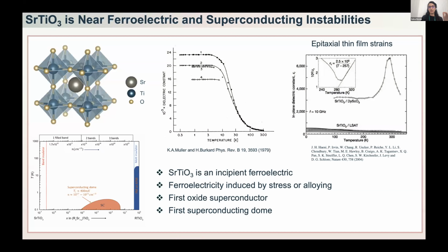Okay, one material system that I am going to focus on in today's talk is strontium titanate. Strontium titanate is close to ferroelectric instability, but it will never become ferroelectric unless you strain it or alloy it with different elements. Also, if we dope it, it will become a superconductor, and it shows a superconducting dome upon doping.